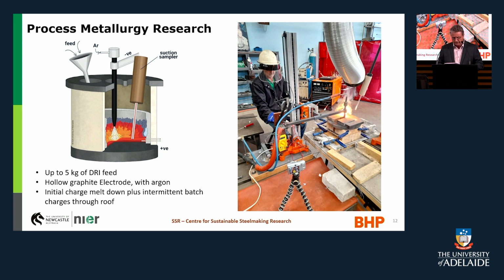So electrode smelting at laboratory scale, holy hell. Well, that's a bit of a challenge. So how do you do that? Electrode smelting has its key feature in that the heating is from the reactor centre out to the sidewall, right? Whereas most of our high temperature experiments that we may have done along the way have been in tube furnaces or induction furnaces or things like this, where the heating mechanism is from sidewall to centre. Those furnaces are not what you want when you're trying to study an electrode smelting furnace, right? Electrode smelting is heating centre to sidewall.